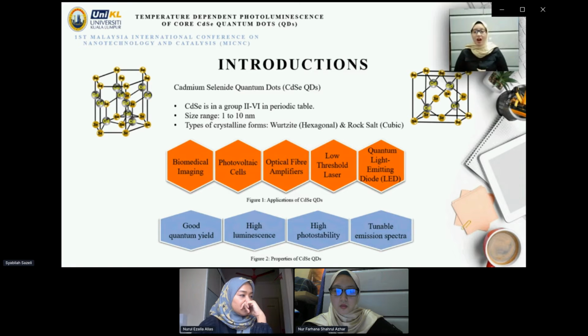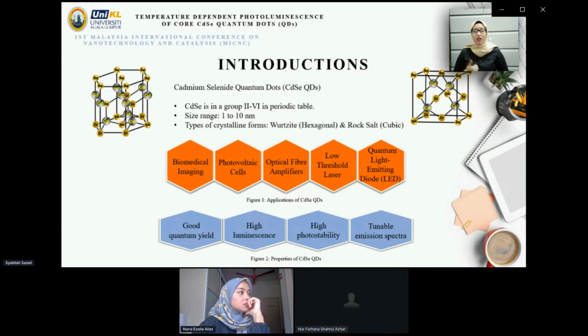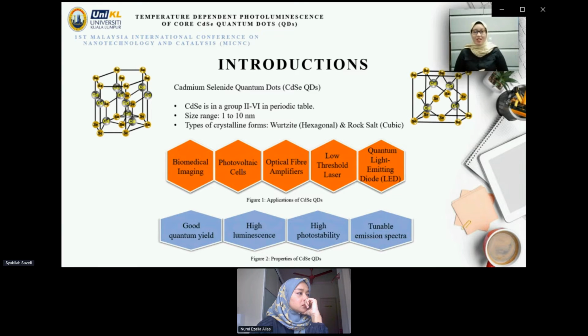Typically, the size range is between 1 to 10 nanometers. In the periodic table, cadmium selenide comprises elements in columns 2 and 6. There are two types of cadmium selenide crystalline form. First, the wurtzite, also known as hexagonal. Second, the rock salt, also known as cubic. The cubic crystalline form can also be converted into hexagonal form by heating the sample at a temperature of 350 to 440 degrees.